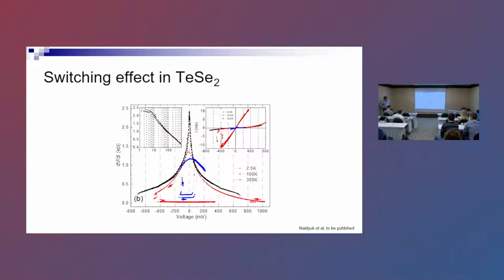There are several reasons for the increase of resistivity. As I told, the first is the increasing response of the electron-phonon coupling, backscattering at the point contact. The second is the thermal effect. But nevertheless, if the voltage is quite small, below some threshold, we always have the same properties and go along the same line. But if we increase above, in this case about 1 volt, then we go to a completely different curve.